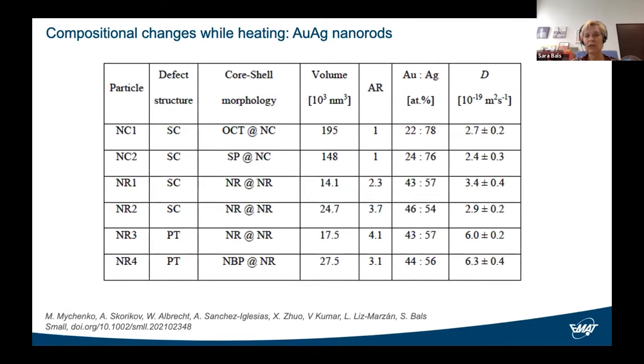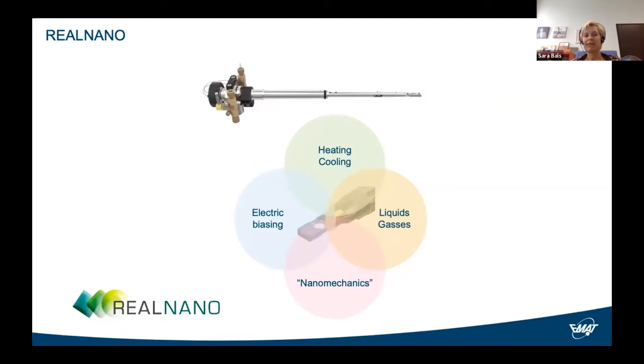And that is also illustrated here in this table, where all the way at the right, you can see the diffusion constant that we extracted from our measurements. And indeed, the diffusion constant for nanorod 3 and 4, the pentatwinned nanorods, is significantly higher in comparison to all of the other systems. So that is an indication that twin boundaries do play an important role during alloying and during thermal stability. Right, so as I said before, all of these investigations were done using a dedicated in situ tomography heating holder.